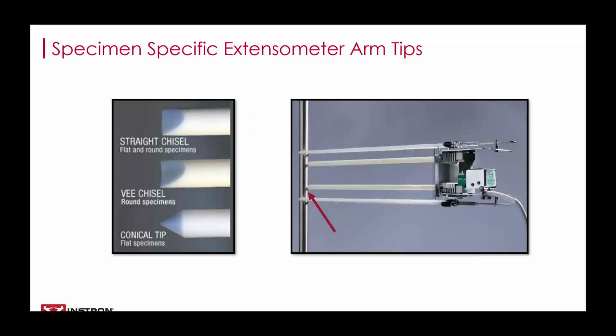Now, for both cold-mounted and hot-mounted extensometers, you'll want to equip with the correct tips for your specimen. If you're testing both round and flat specimens, the straight chisel can accommodate both. However, if you're only testing one or the other, it really makes sense to optimize here. If you're only testing flat specimens, the conical tip is recommended because it reduces the risk of multiple engagement points from each arm. And if you're using round specimens, the V chisel is recommended. The groove of this style allows for self-alignment of the arm on the specimen, which can improve the fit for each test.